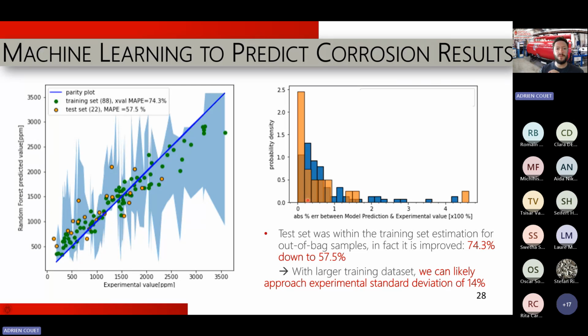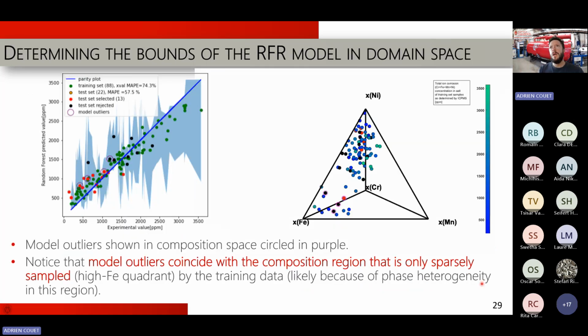And then if you add those 22 alloys to the 88 alloys that we had done before, you can also reduce the error of your machine learning algorithm down to about 58%. And when we repeated tests of the same alloy to look at the experimental error of our results, it was about 15% or 14%. So we think that as you add more and more, and we're working on that, you can get down to 15% error.